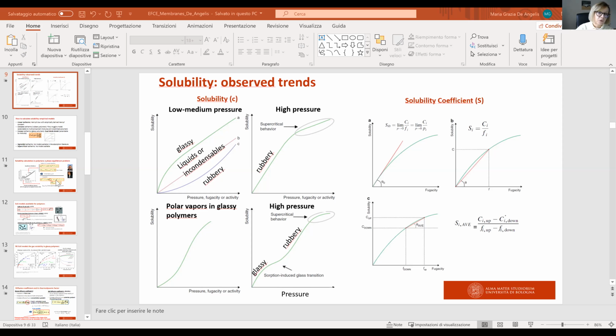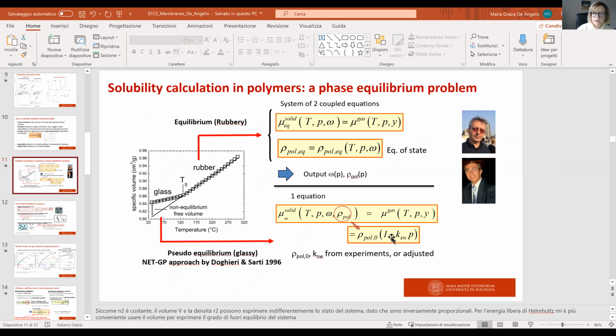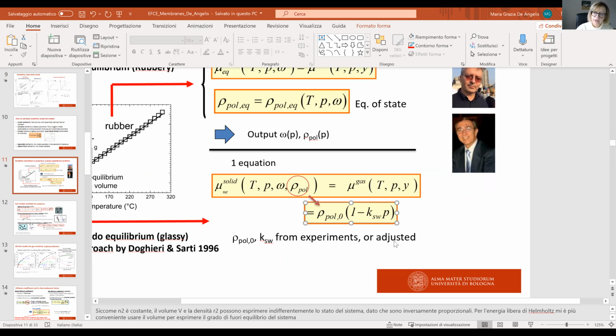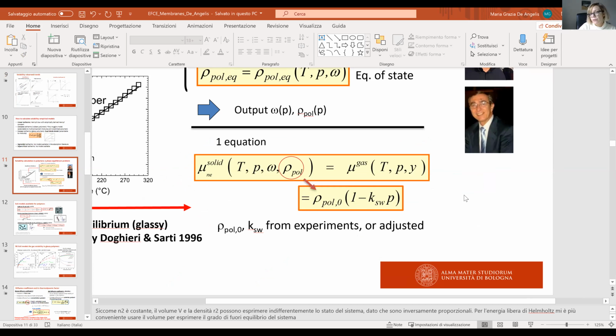So in that case, you can rely on, for instance, this equation reported here, based on which the polymer density is a linear function of the gas pressure. This is based on experimental observation that the density of the polymer decreases with increasing gas pressure. And this approximate behavior is consistent with reality in several cases. So based on this law, you just need one swelling coefficient that gives you the slope of the density with the pressure to perform the simulation. But indeed, it is a datum that needs to be provided to the solubility model for having a correct estimate of the solubility at high pressure.